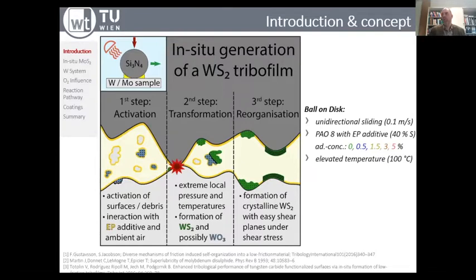So first, this is an overview sketch of the in-situ generation of these tribofilms. I will come back to this during my talk, step by step. The basic setup that we selected is a ball-on-disc setup under unidirectional sliding, with a sliding speed of 0.1 meters per second. As I said before, we use a polyalpha olefin as a synthetic lubricant with an EP additive as a sulfur source. The additive concentration has been varied from 0% to 5%, and all the tests have been done at elevated temperatures up to 100 degrees C.